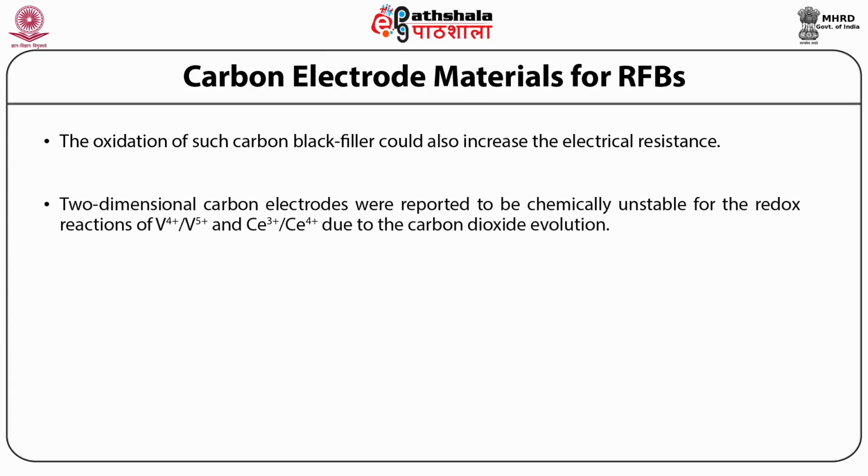Two-dimensional carbon electrodes were reported to be chemically unstable for the redox reactions of V4+, V5+, and cerium 3+ and cerium 4+ due to the carbon dioxide evolution.